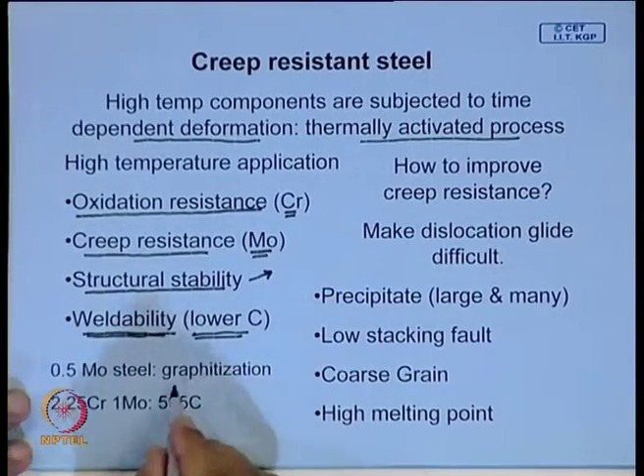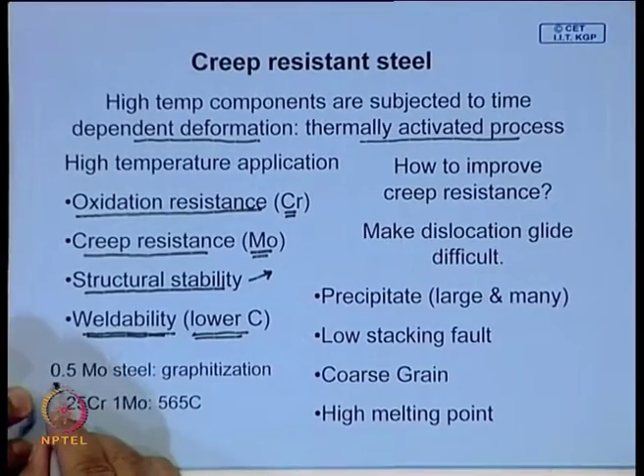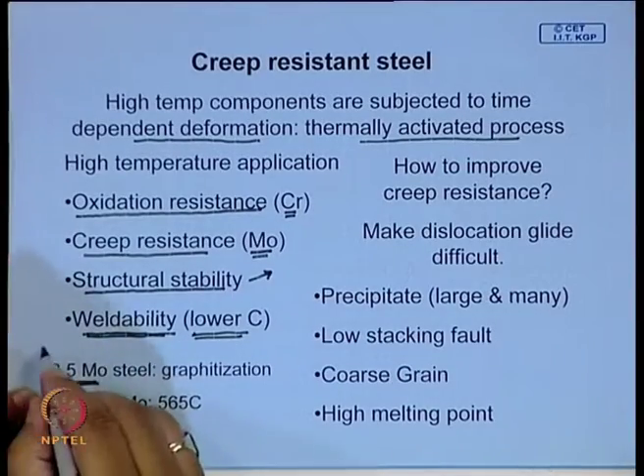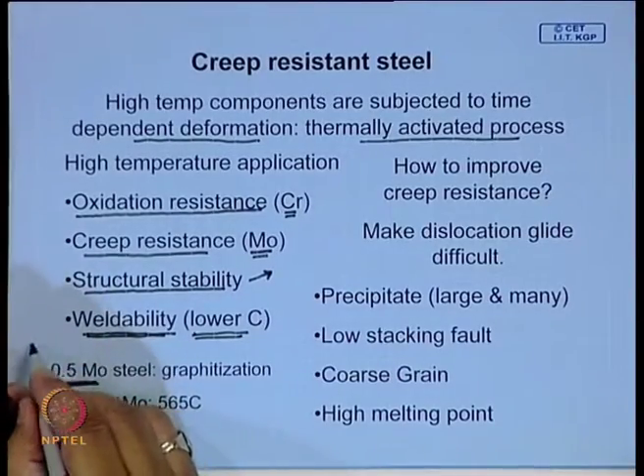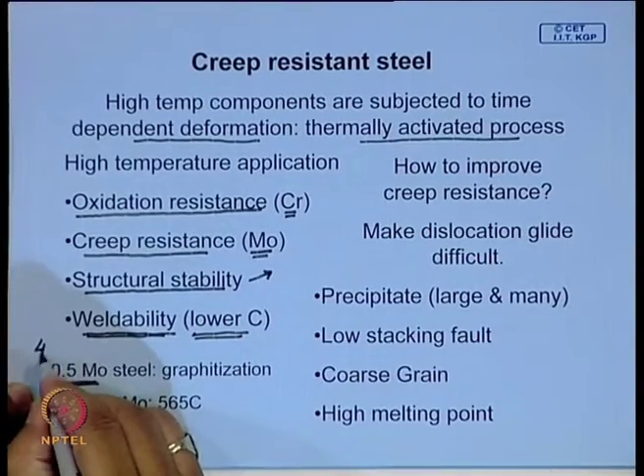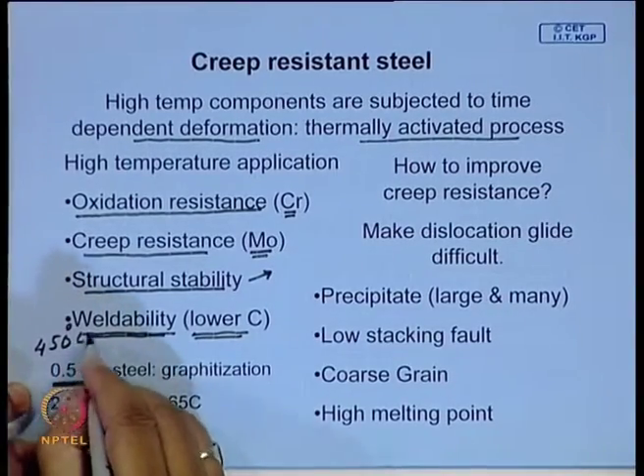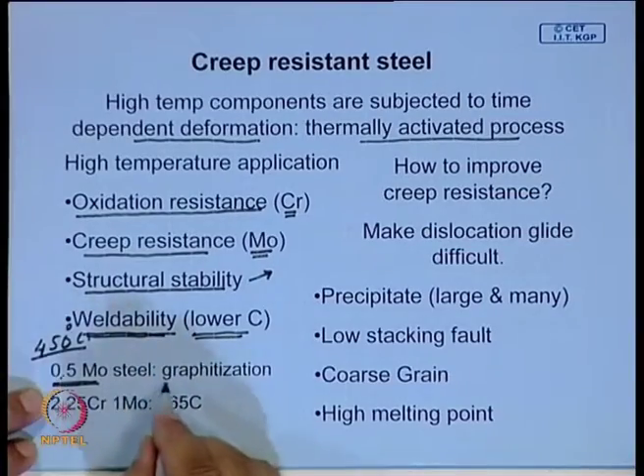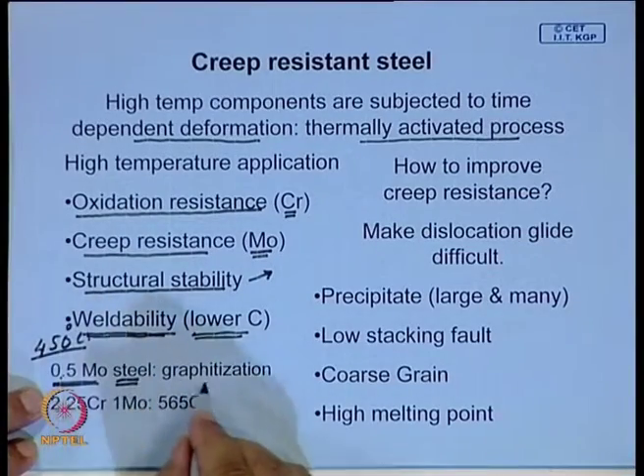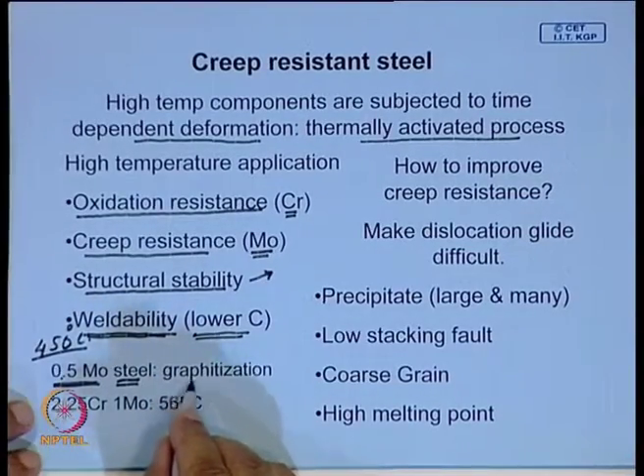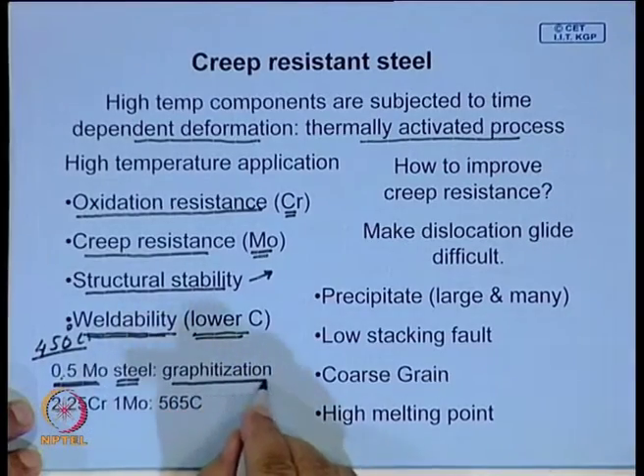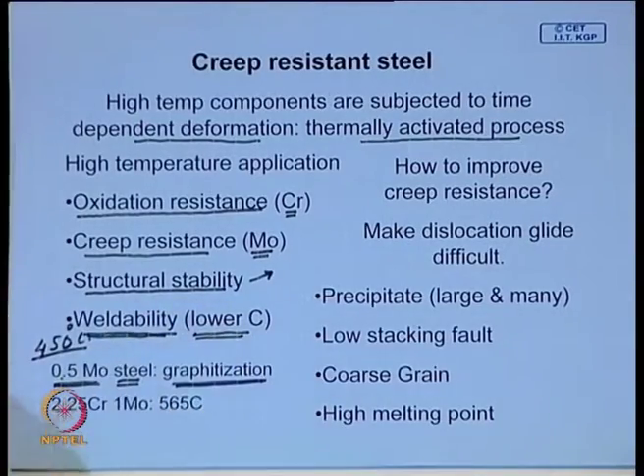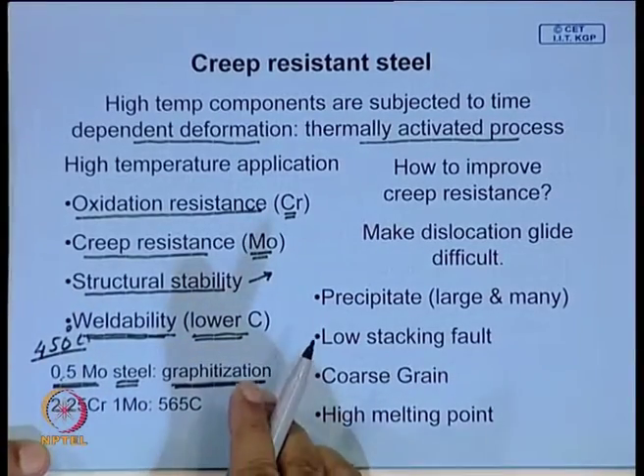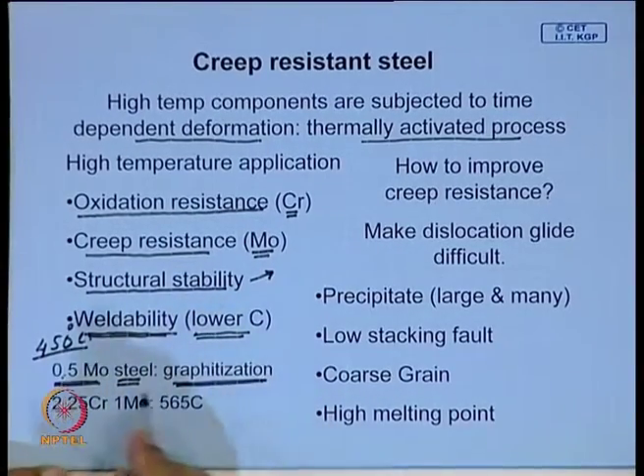Now, the earliest creep resistant steel was for older power plants which do not operate at very high temperature, maybe around 450 degree centigrade. There, half moly steel is good for creep resistance, but this is known for a problem called graphitization. Prolonged use at high temperature, carbide gets converted to graphite. So, that is a major problem.